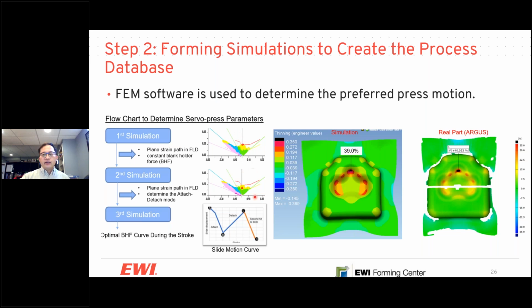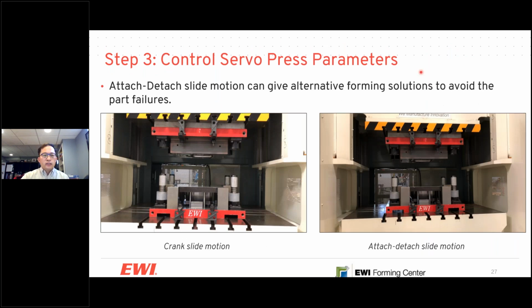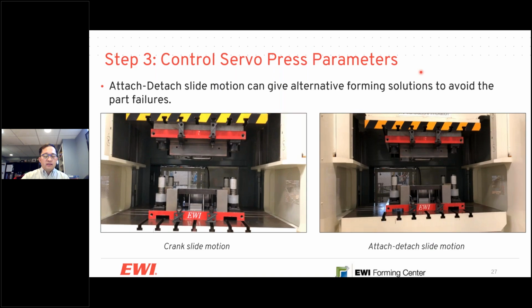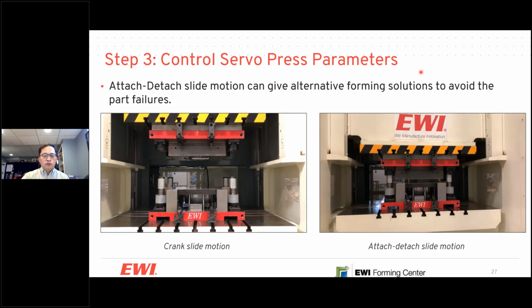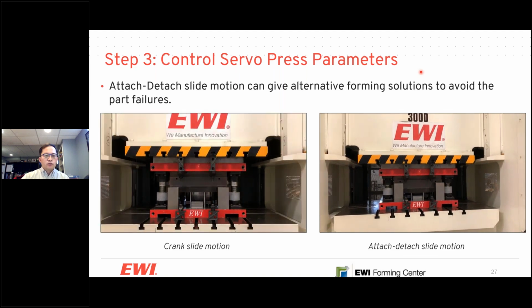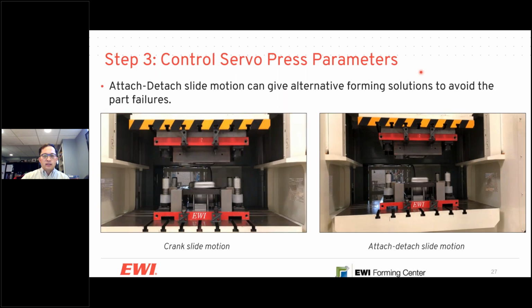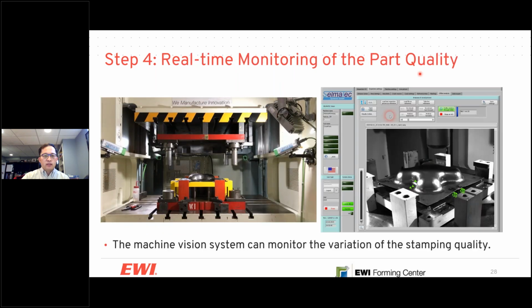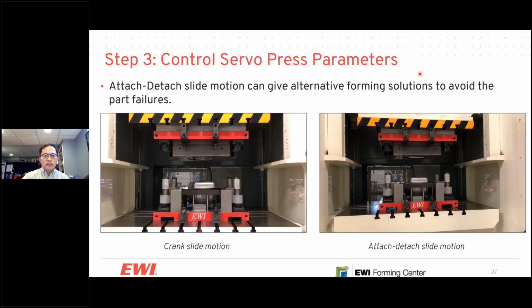Using the FLD diagram, we also have a pretty good correlation between the simulation results and the real scanned part, with a maximum thinning of 39% predicted by simulation against a 40% maximum thinning measured with strain measurement tools on the actual panel. With that information, we developed and validated the press setting. The motion on the left side is the crank slide motion. There is some delay in that video, but we can run that at up to 12 or 16 strokes per minute.